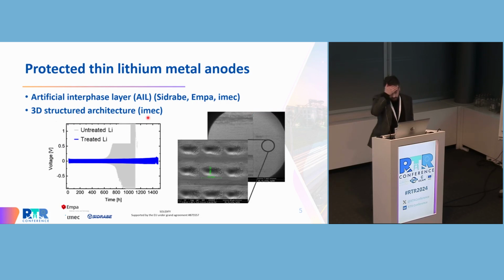The lithium metal anode is the last component which we have been optimizing. In principle, the cell is assembled in a discharge state, so we could use a lithium-free electrode. However, we need an excess of lithium in order to mitigate the irreversible loss of lithium caused by parasitic processes in the cell during the first cycle.